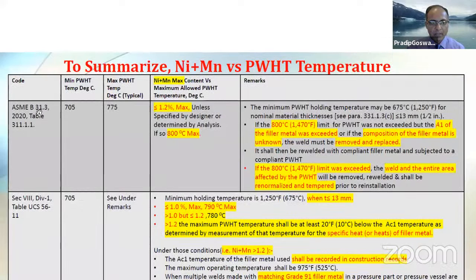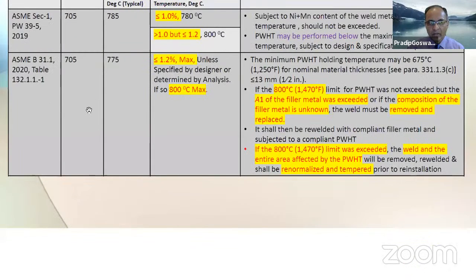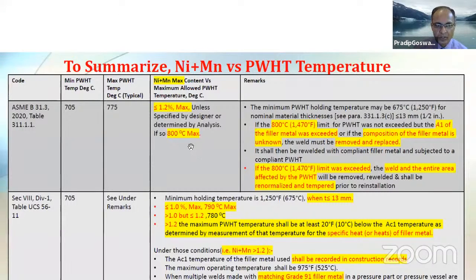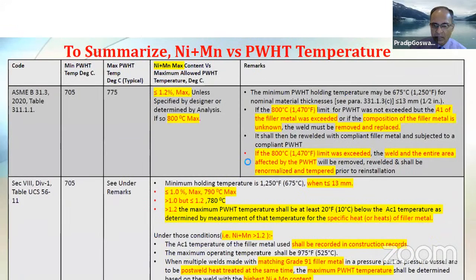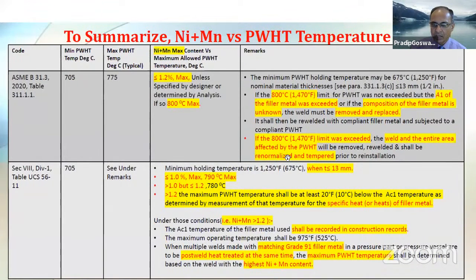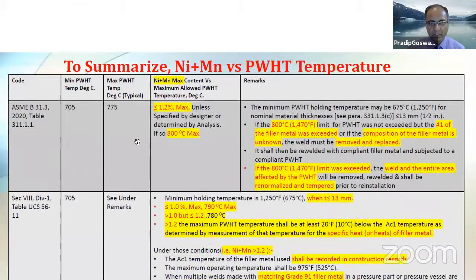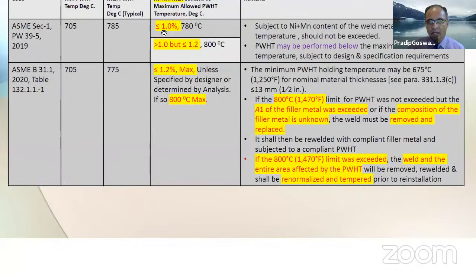Incidentally, you will see that piping codes B31.3 and B31.1 think alike. That means basically a uniform level of specifications is allowed by two different code committees, or two different codes, but they're basically the same, almost word by word. ASME Section 8 Div 1 is a bit different, but coming back to the nickel plus manganese content, the general summary is that it should be typically between 1 to 1.2% maximum, as per the latest specifications, or as per the latest ASME code requirements.